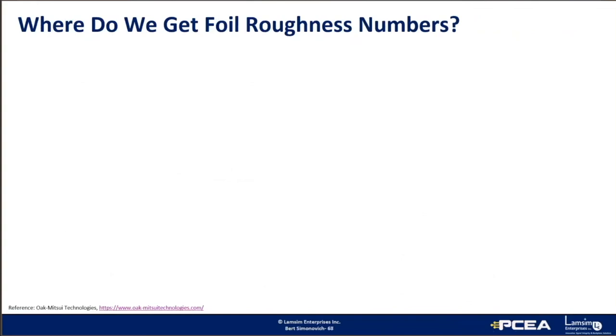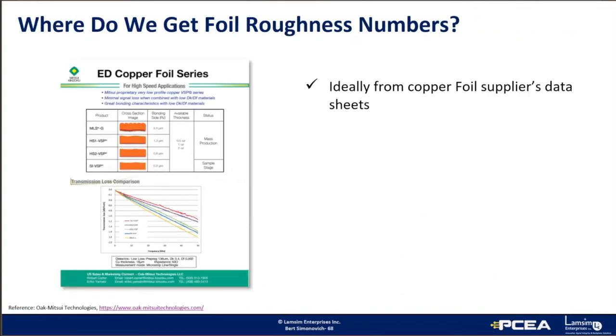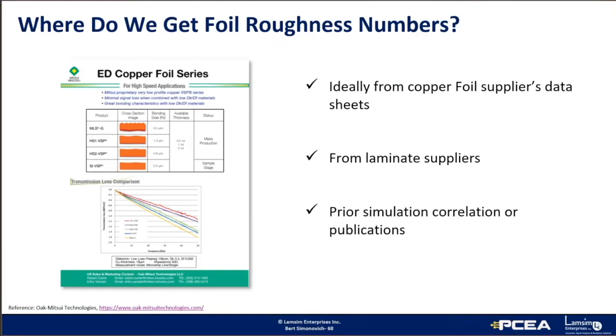So where do we get the foil roughness numbers from? Well, ideally you would get them from foil suppliers data sheets. For example, this is data sheet from Mitsui showing 4 common roughness profiles. Another source can be from laminate suppliers, but you have to be careful because not all laminate suppliers interpret the roughness numbers correctly and often get RZ and RQ mixed up. It's best to contact them directly and ask for the actual foil type from the foil suppliers that they use. And finally, you can get these numbers with prior simulation correlation or other publications in the industry.